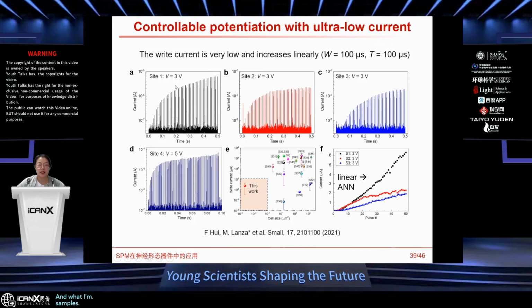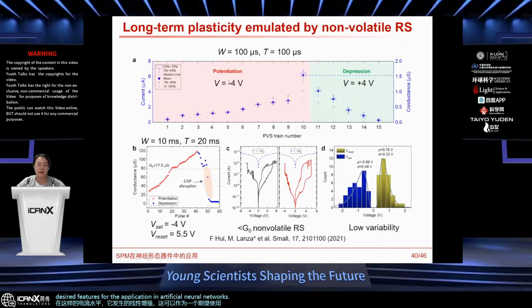And by tuning the amplitude and the width of the pulse, we can also get repeated potentiation at different locations. By comparing with previous literature, this work represents a significant advance in terms of the write current and the small cell size regarding the integration density. At such a current level, linear potentiation happens, which can be used as a desired feature for applications in artificial neural networks.